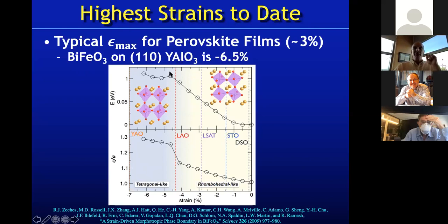But what you can see in the first principles calculations is there's another ground state over here. So there's a parabola in strain around the bismuth ferrite rhombohedral phase, and then there's another parabola in strain around this tetragonal-like phase, this super extended ferroelectric phase over here, and that lowers the barrier. Bismuth ferrite is amazingly malleable, but it really helps when you don't have to pay the full energy cost to do the 6.5% strain. So I'm just saying that there are some systems where you can get lucky and go to even higher strains.